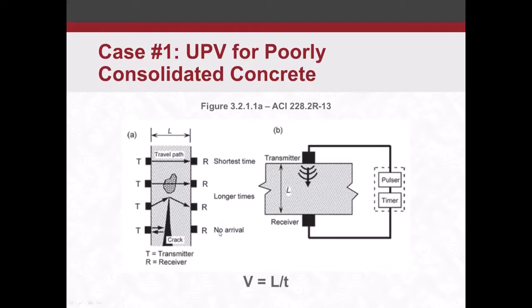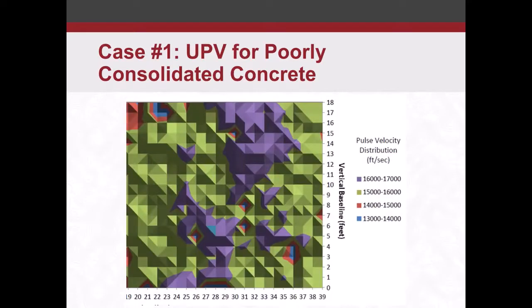But generally speaking, this is what we do. We've got a transmitter on one side, a receiver on the other side. We send a pulse, and we identify the time that it took for that pulse to travel from one side to the other. And then we generate kind of a plot like this. Depending on what our velocity distributions are, these numbers might change. In this case here, we've got 13,000 up to 16,000-plus feet per second.